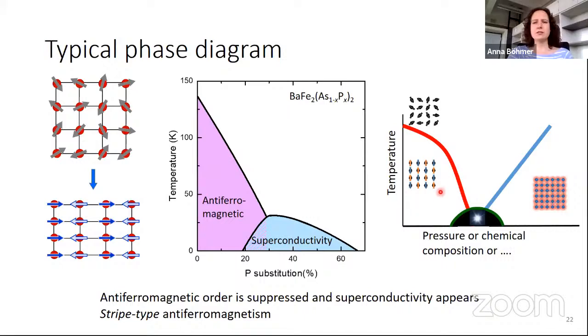So the question here, and the question that we are very much interested in, is what is this phase that is suppressed to get the superconductivity? And here we have a magnetic phase, we have an antiferromagnetic phase, which is a little bit special. What we find is the magnetic moments, which are disordered at high temperature, they point in any direction. They order in this way that they are parallel along this one stripe, and then antiparallel to the next ones. So we have a stripe type antiferromagnet. So basically a ferromagnetic direction and an alternating direction here.